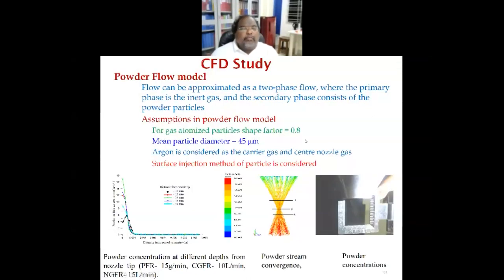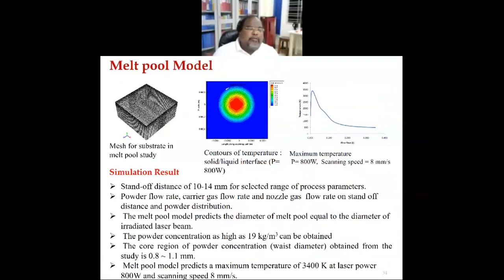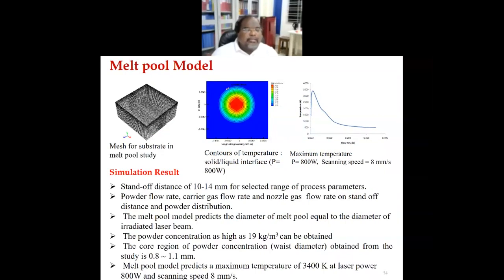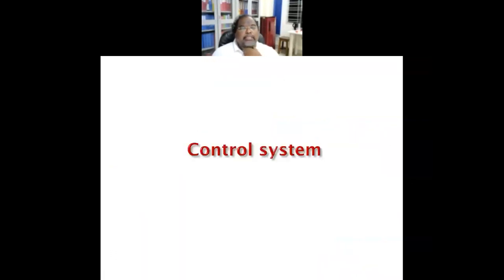And then these are a few more assumptions. After getting this value, we did more targeted calculations to get the exact value. From the simulation results, this is the summary we got from the exact calculations. We selected a range of 10 to 14. Then we obtained this powder concentration, and we got these parameters. Core regions were somewhere between 0.8 to 1.1 mm, and the melt pool, of course, was at 3400 K, with the laser at 800 watt. We also used 8 mm/s for the scanning speed. So this is the information we got from simulations, which we could utilize for development.